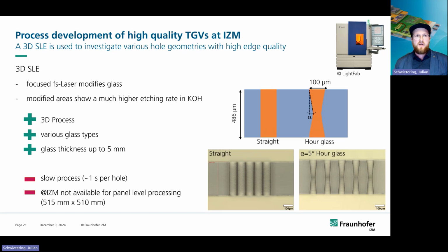The advantages are that we have a 3D process. As you can see here, we can make hourglass shapes for the TGVs, and this can be important if you want to fill them afterwards with copper. But we can also have really straight TGVs, and this can be important for high frequency applications. With this 3D process, we can have various glass types, and we can process glass thickness up to 5 millimeters.